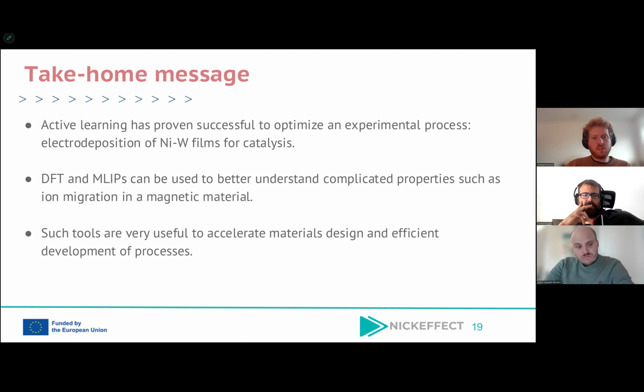We also use DFT and machine learning interatomic potentials to better understand properties that are quite complicated. The diffusion of oxygen atoms or ions in a system is not easy to do, but we can do that using DFT or machine learning interatomic potentials, and we can even do that in magnetic materials that are more difficult to simulate than, let's say, silicon, for instance. So these tools are indeed very useful to accelerate materials design and also the efficient development of processes. And these are the tools that we use in NICKEFFECT.